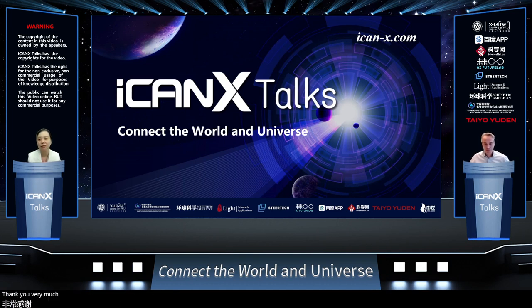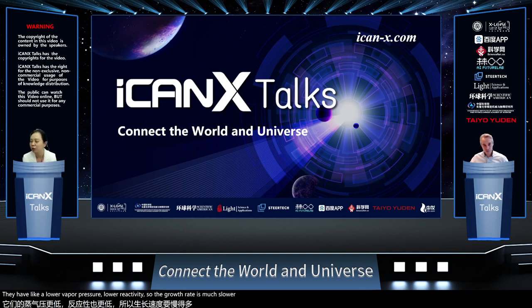Thank you very much. That's definitely a very interesting question. In my opinion, molecular layer deposition is sometimes similar to atomic layer deposition. They sometimes can share similar equipment and similar surface chemistry. I actually run molecular layer deposition in my lab as well. But I found that because I'm dealing with a lot of organic molecules instead of the metal organic ones, they have lower vapor pressure and lower reactivity, so the growth rate is much slower compared to a lot of ALD processes.